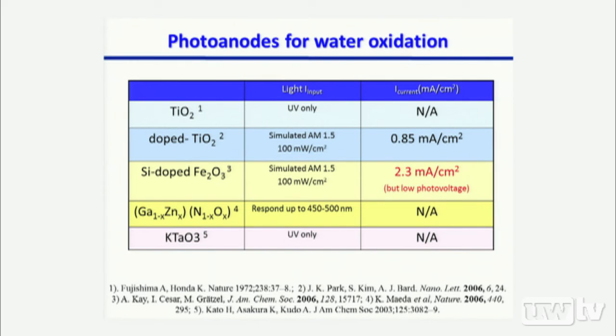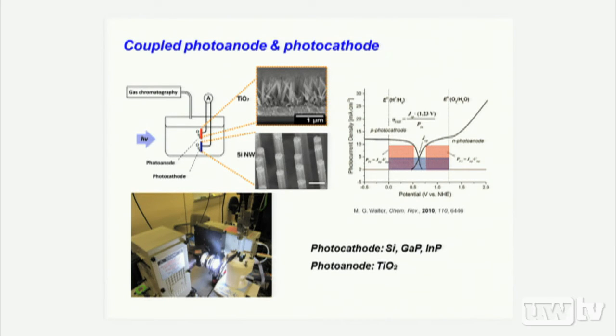On the photoanode end, it's much more challenging. As I mentioned, in the photocathode we can easily get up to 700 millivolts in photovoltage, and the photocurrent can be 30 milliamp per square centimeter. On the anode end, we don't have such a material. The silicon-doped iron oxide from Mike Grätzel's group can go up to 2.3 milliamp per square centimeter, but it's far off in terms of photovoltage. We have been experimenting with different high surface area electrodes, utilizing the photocathode, and on the photoanode end we're using TiO2 as our model system.